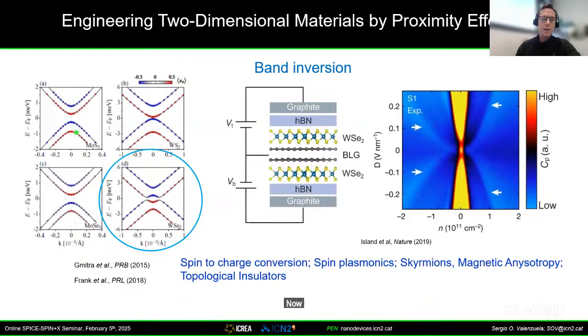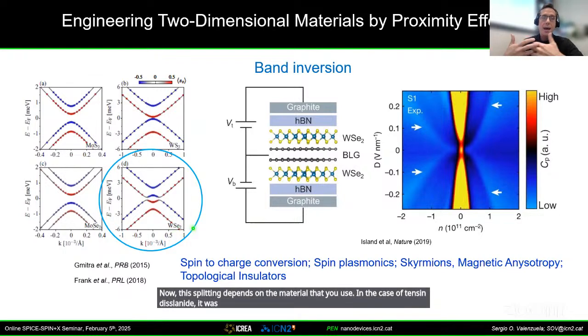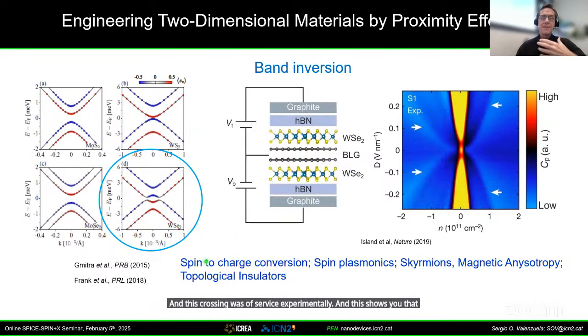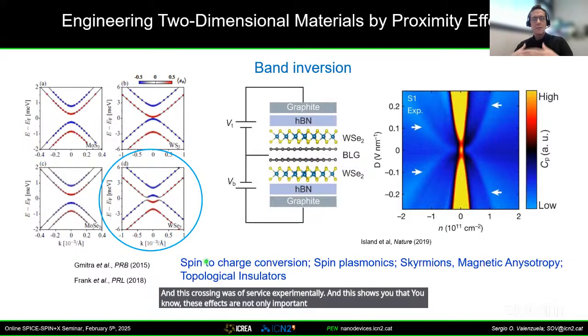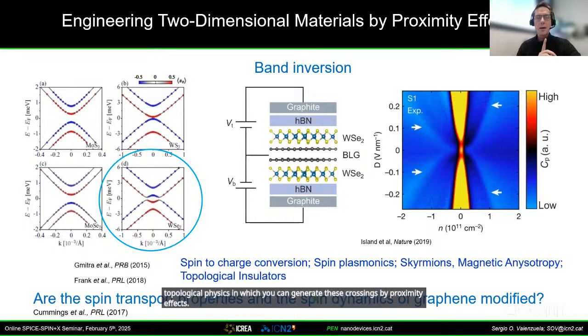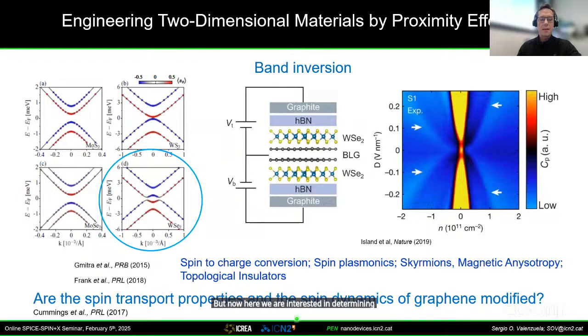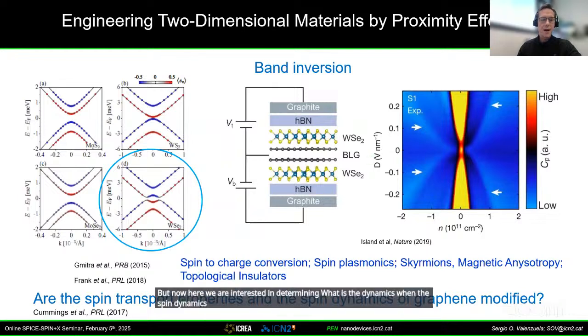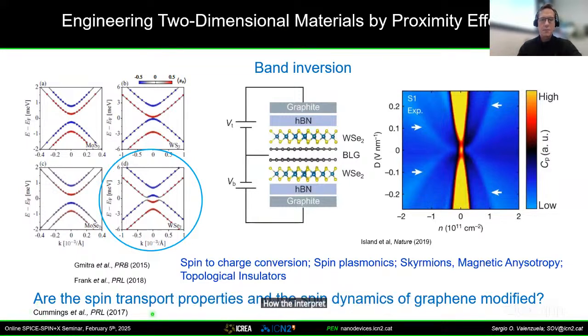Now this splitting depends on the material that you use. In the case of tungsten diselenide, it was predicted that you can even have a crossing between the bands because of the spin orbit coupling. And this crossing was observed experimentally. And this shows you that these effects are not only important for spintronics and the fundamental ideas of spin to charge conversion, anisotropy, and so on, but also for topological physics, in which you can generate these crossings by proximity effects. But now here we are interested in determining the spin dynamics when graphene is modified. This was theoretically described by the group of Stephan Roche before we did the experiments. I will show you the experiments and then go back to how the interpretation matches the prediction done in this paper here.